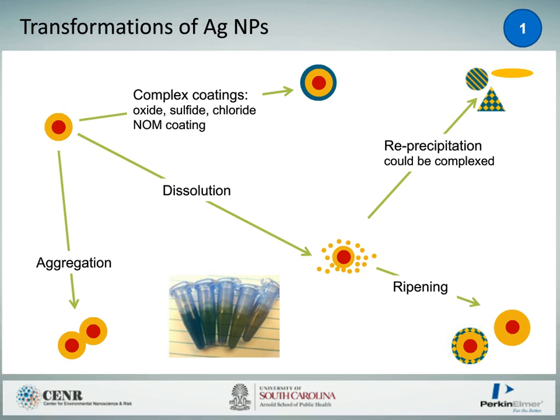So the transformations of silver nanoparticles, as Dr. Lead mentioned earlier: we can have aggregation, where they'll stick together and sediment out from our suspension. We can get complex coatings, and as you mentioned earlier, having oxides, sulfides, chlorides, or natural organic matter coating, or we can have a process like dissolution. So it can dissolve, and from that you can have reprecipitation either on its own or with complexes, forming different shaped nanoparticles, or you can get an Ostwald ripening effect where the particles that are still in suspension will grow